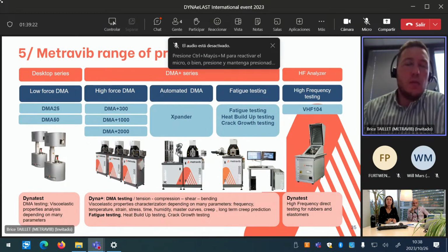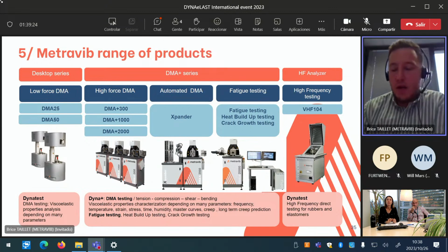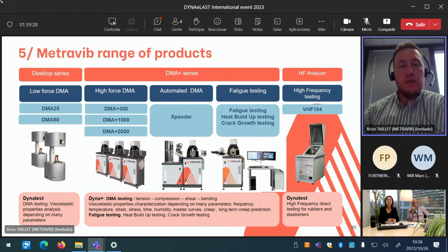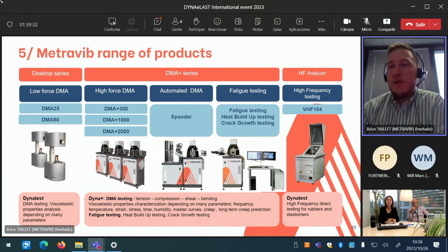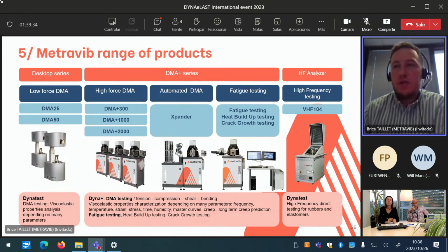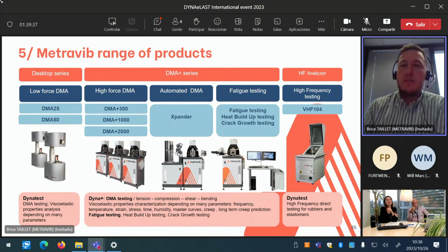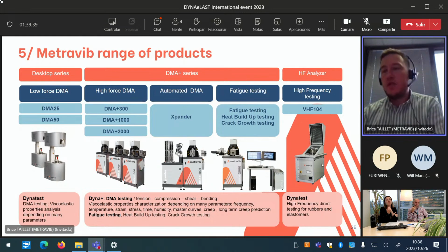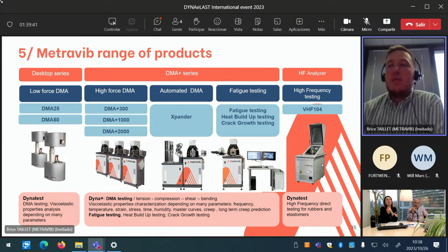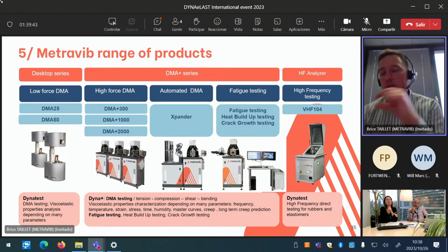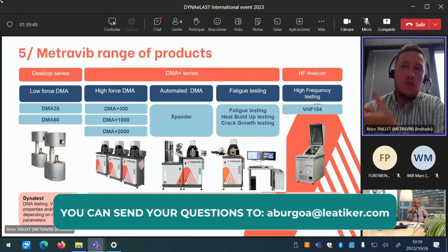Just to explain, computing a master curve in DMA requires maybe 5 or 6 hours of test with a lot of liquid nitrogen consumption. And for VHF, we just need 15 minutes to get the whole viscoelastic spectrum up to 10 kilohertz. So it's much more convenient. But the limitation is the shape factor because we are only able to work in compression mode. We don't use any tension mode or any shear mode with VHF. That's a limitation.